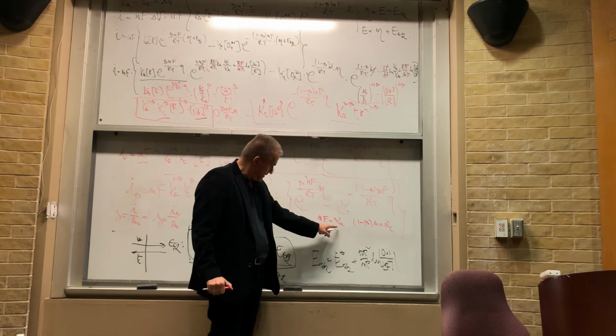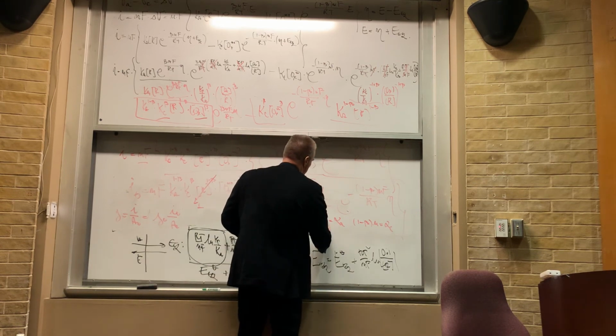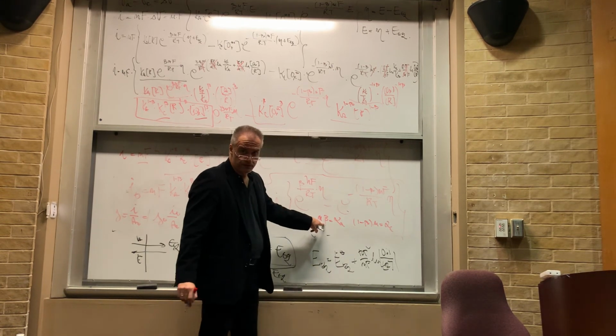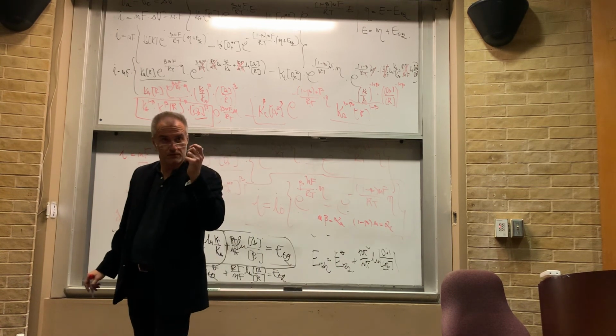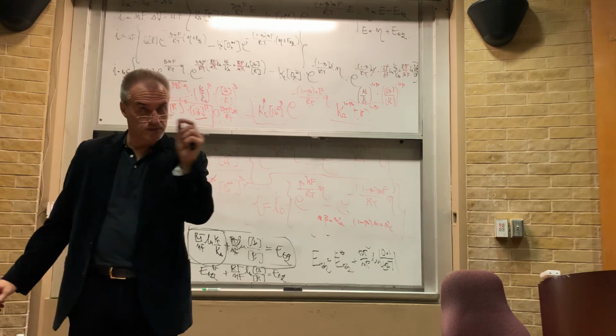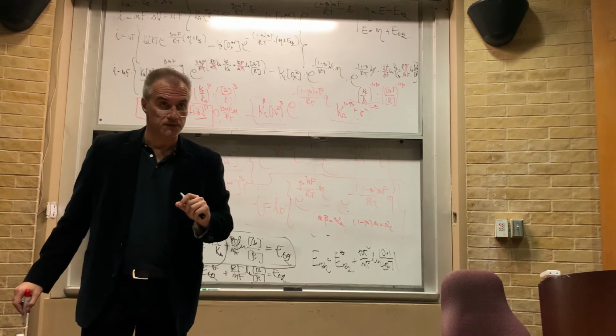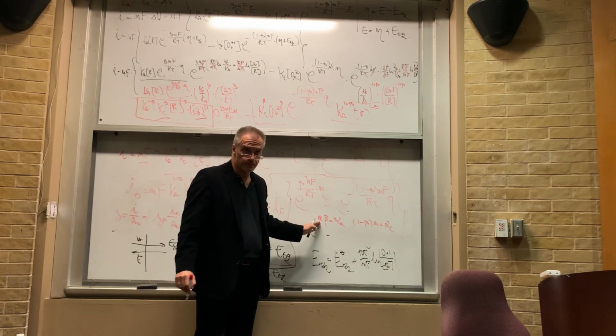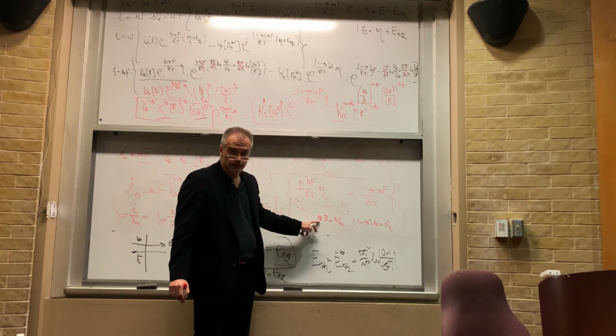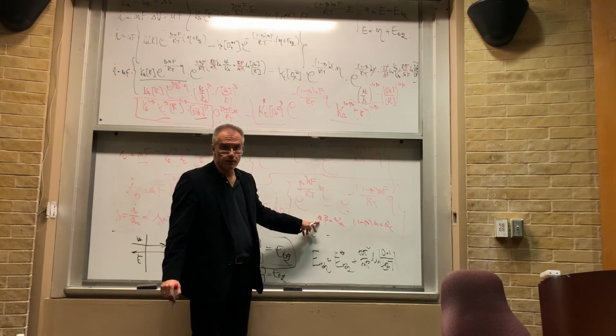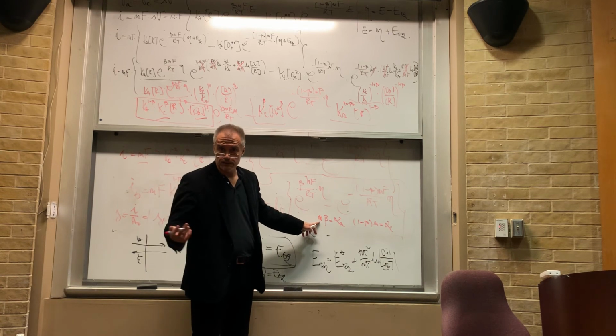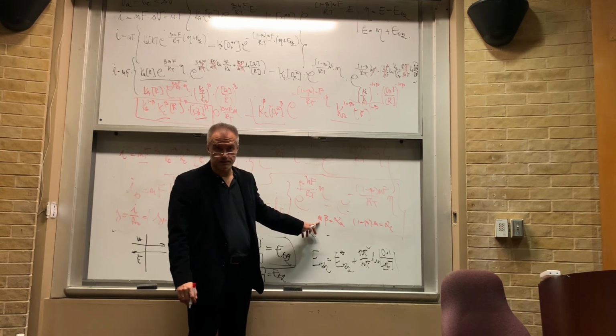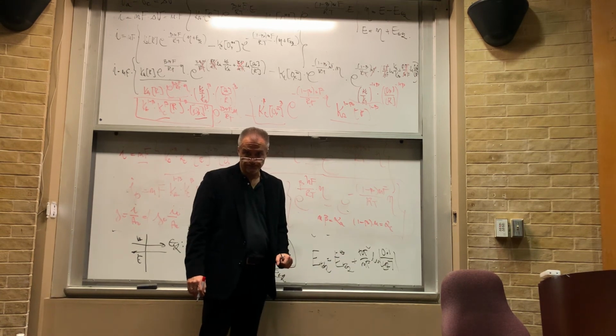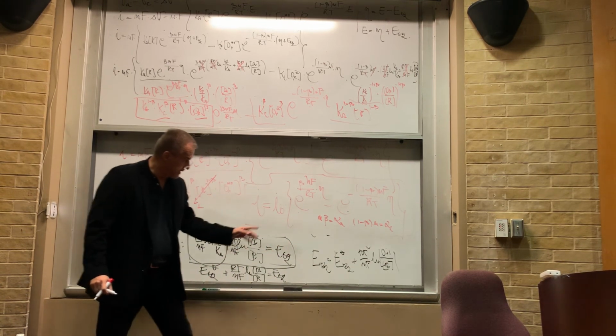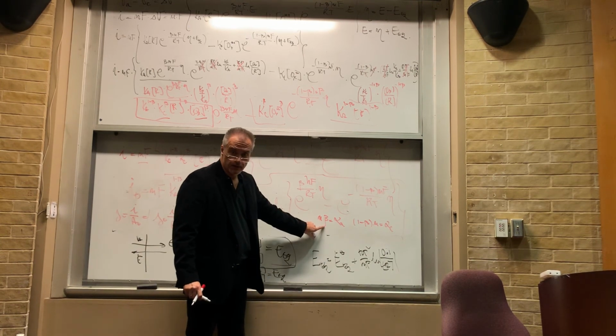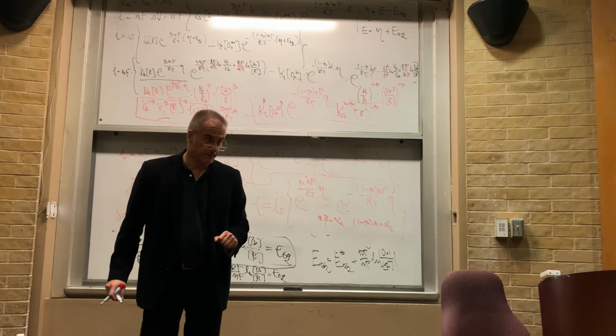What it really means is that alpha anodic is a function of, this is n beta, sorry, of the beta, which is between 0 and 1, but n is the number of electrons or oxidation state of your ions, or the number of electrons that are transferred across the interface per every atom you deposit. So, beta between 0 and 1, alpha depending on n could be between 0 and 2, 0 and 3, depending on whether you have 3 plus ions like chromium 3 plus deposition, etc. Same thing here, right? Okay. So you do understand the difference between anodic and cathodic coefficients and symmetry factor beta. It's a fundamental difference. Okay.